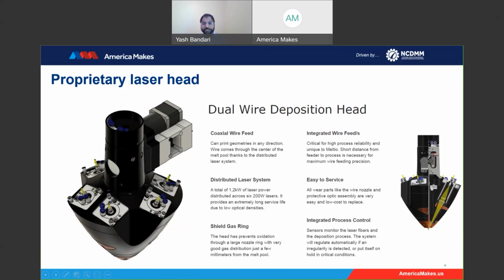There are some technologies where you have the wire coming in from an angle, but in those situations, if you move in different directions, the melt pool size is pretty much compromised. But in the case of coaxial, it's like a MIG torch. You can print any geometries in any direction. And the second thing is we've got 6 off-axis lasers. These are fiber-coupled diode lasers, and each one of these lasers is capable of emitting 200 watts of laser power. So the total laser power is about 1.2 kilowatts.